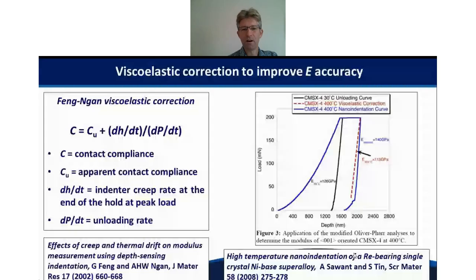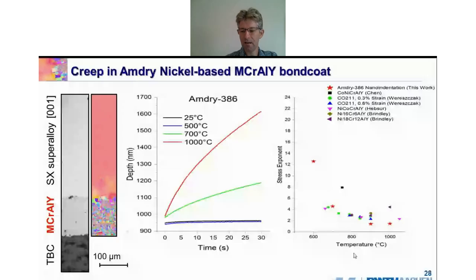These tests were done with diamond, which was possible because it was under this 500 degree limit. Obviously the applications of these nickel-based superalloys and the bond coats in jet engines are far higher than this. So it's nice to be able to test at higher temperatures, and for that you need to go to vacuum, and you need to use, in this case, sapphire indenters, because as I say, the cubic boron nitride indenters react with these samples, and they effectively blunt the tip, changing the area function too quickly.